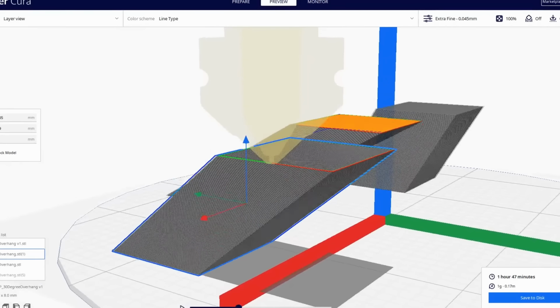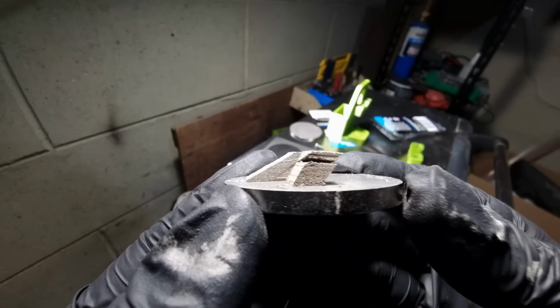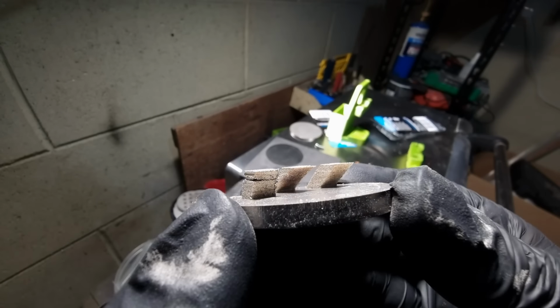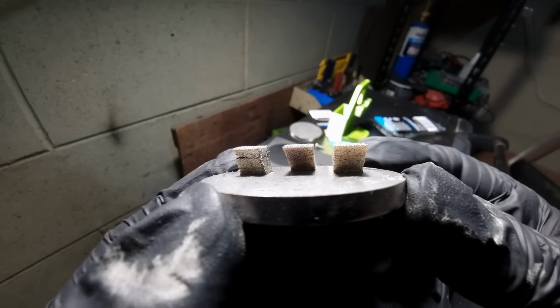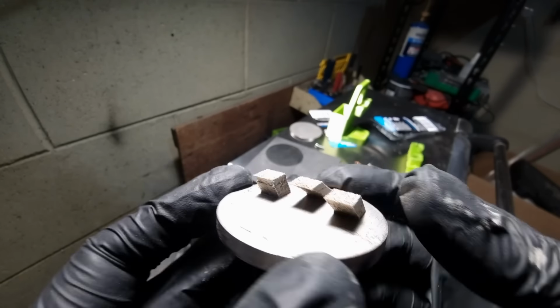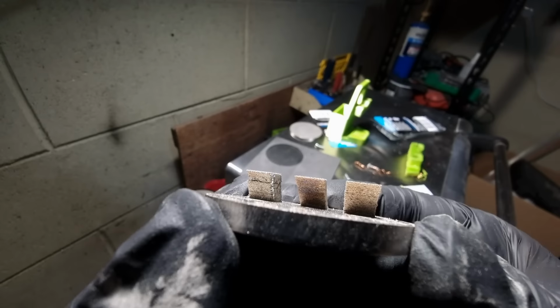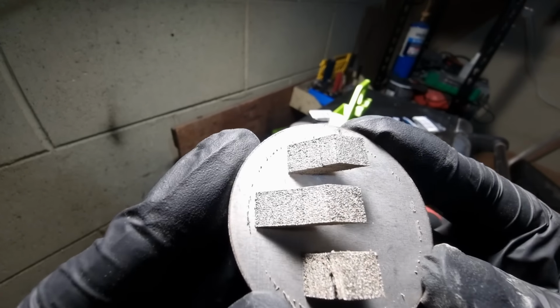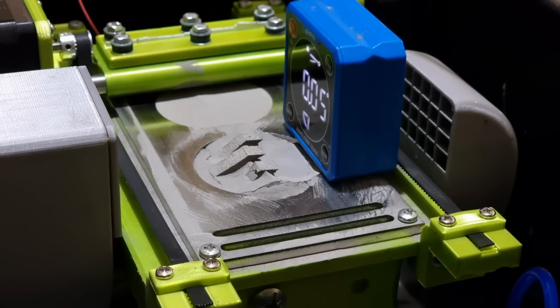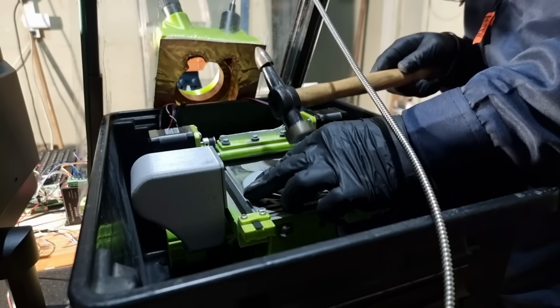I also tried printing some overhangs using the same parameters to figure out what the limitations of this setup were, and as you can see, I was still battling with the system crashing multiple times per run. It seemed happy at 50 degrees away from the build plate, but at 40 and especially 30 degrees, it was reaching its limits. I was also witnessing my powder bed begin to break apart as using a hammer to level the substrate had taken its toll.